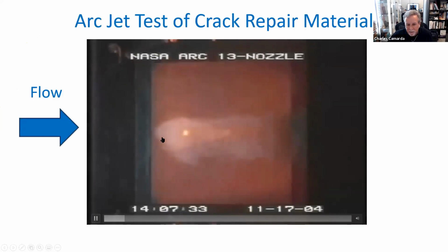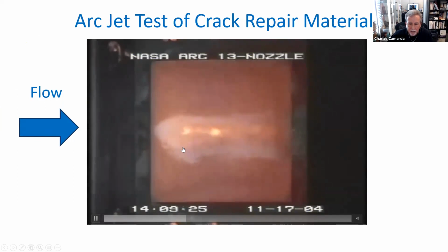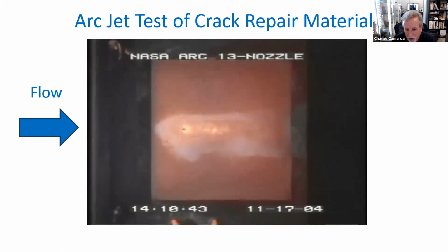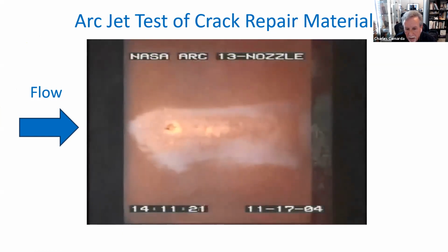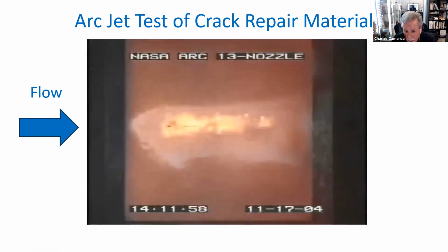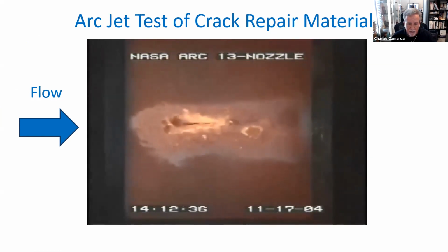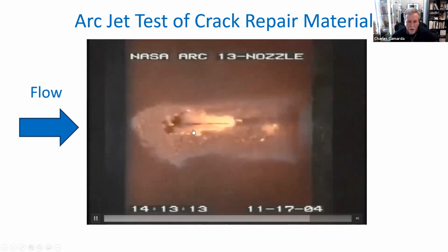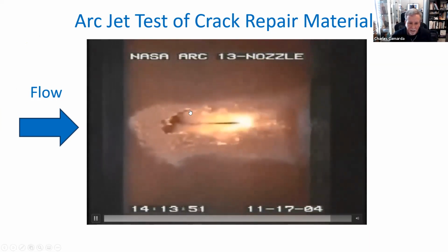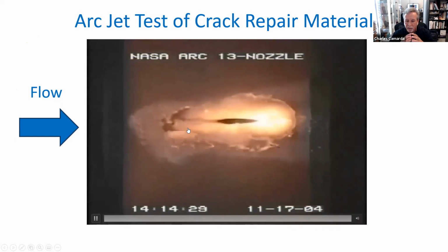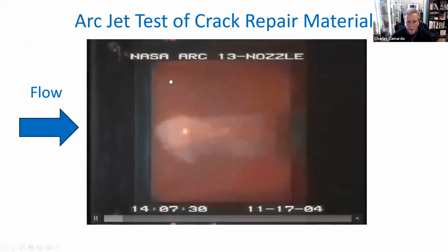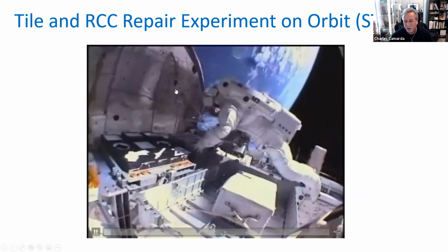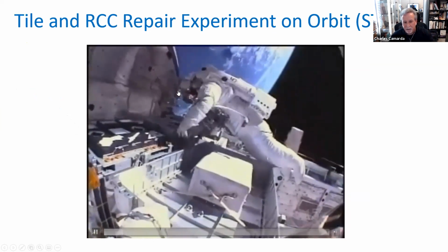But when we tested this material, right, over a small crack, the flow is from the left to the right. You see it's getting very hot. And as the material starts getting hot, even though it's forming into a ceramic material, it's becoming fluid, it's becoming viscous, and it's starting to separate and move away in the flow. And as that happens, then this crack begins to grow. This opens up, and you have a problem. So we tested lots of these ideas.